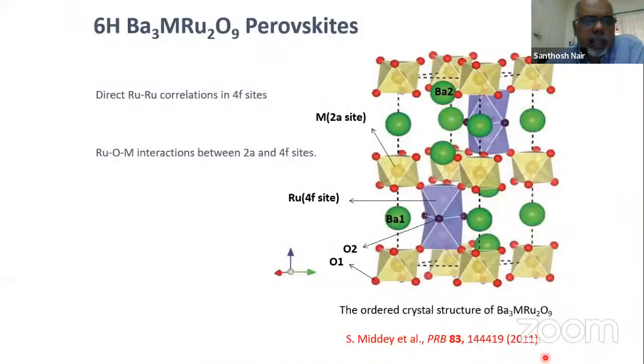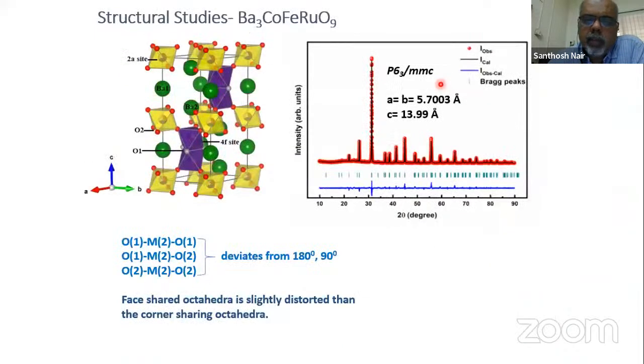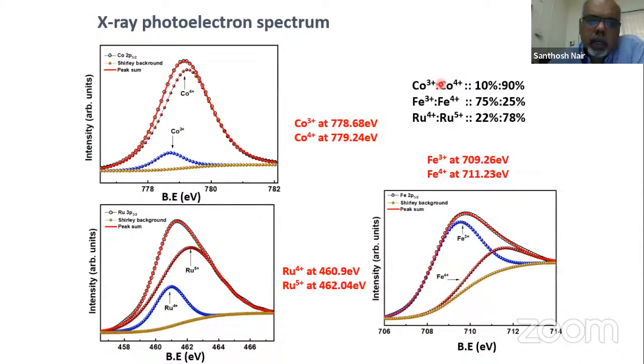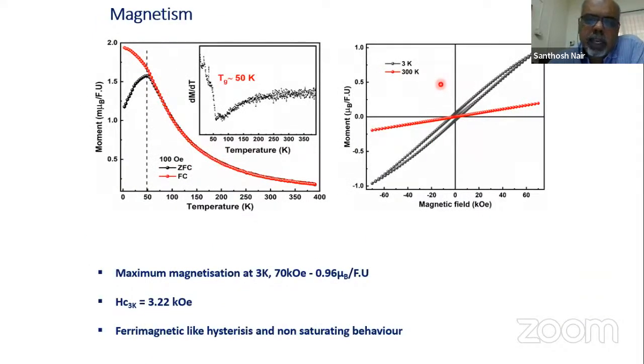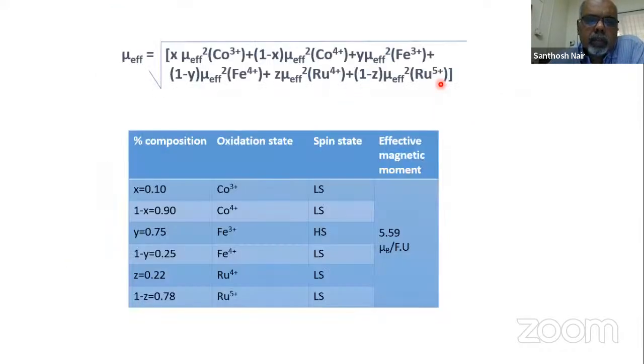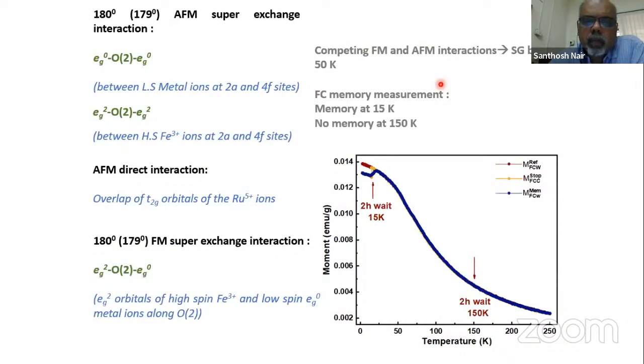I will briefly explain, without going into the detail. We took up the hexagonal system, where you have the face-shared dimer and the corner-shared octahedra. Here you put mixed-valent iron and cobalt, and ask whether we get exchange bias in these. We got a single phase system, and we see mixed valence in all 3 ions. That makes the system extremely complicated, and we see a hysteresis loop at lower temperature. At very low temperature we think it's a glassy phase, and we have done memory studies to show that the memory effect exists in this system.